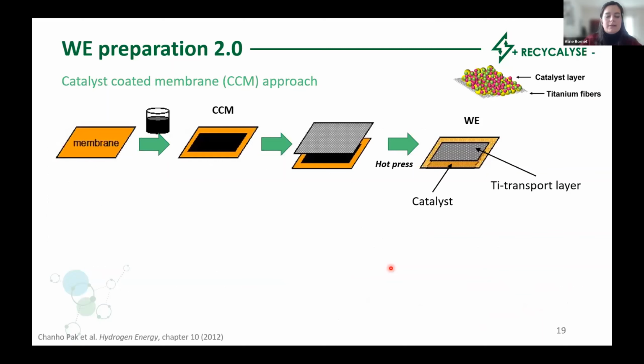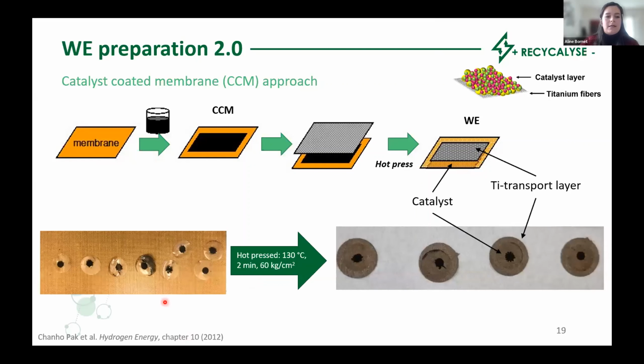And to do that, we had to rethink our way of preparing the working electrodes. As this titanium-based transport layer does not have the MPL, we cannot use the vacuum filtration approach. So we used the so-called catalyst-coated membrane approach, or CCM approach, where the catalyst is first sprayed or deposited on the membrane and then hot pressed on the transport layer. And in my case, it looked like this. We used the Nafion membrane and we sprayed the catalyst with a spray can, and then we hot pressed them onto the titanium transport layer.